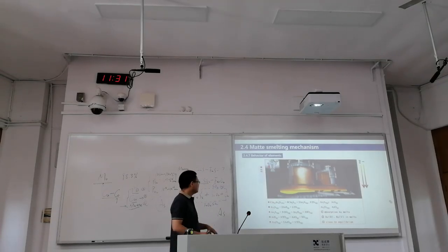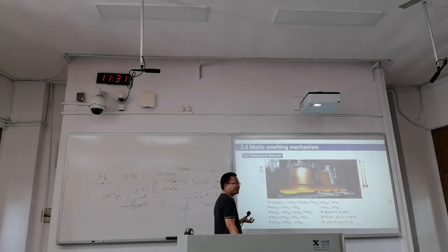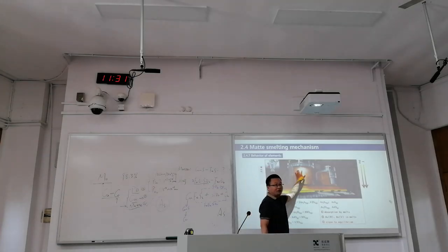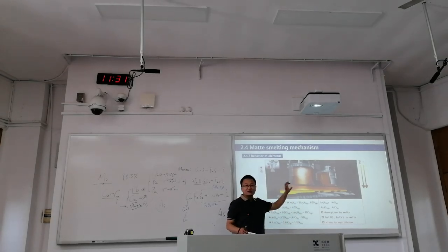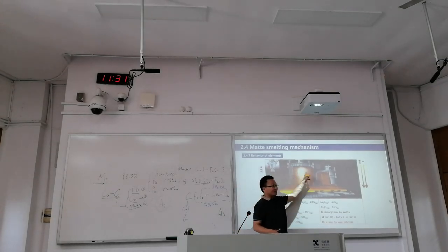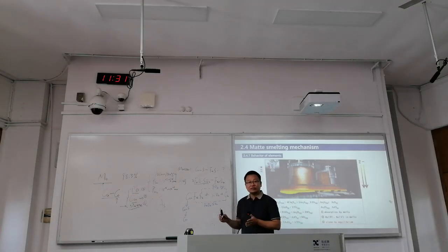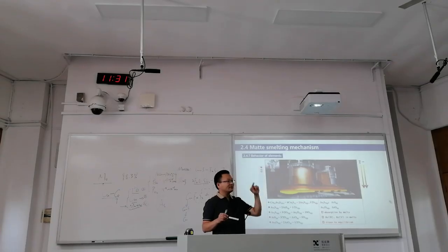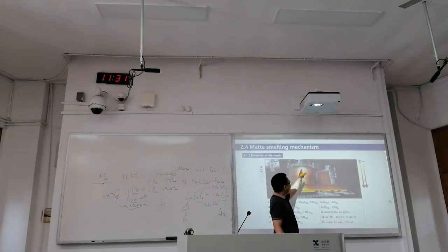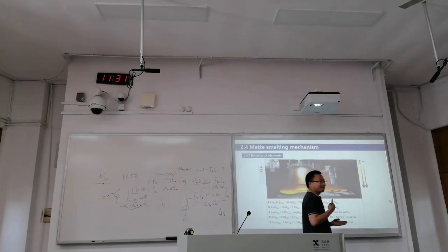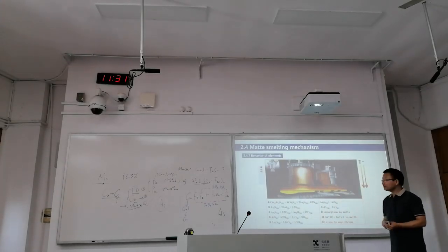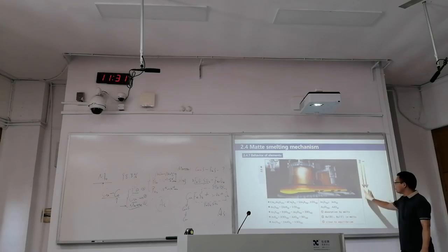A lot of oxidation reactions will happen, right? So when you have sulfides, we have oxygen at high temperatures. Oxygen will react with our sulfides. So these are very intensive reactions in this region. So if we have oxidation reactions here, energy is released. The temperature will keep increasing. So in this furnace, this part is the hottest one, and richest with oxygen and materials.